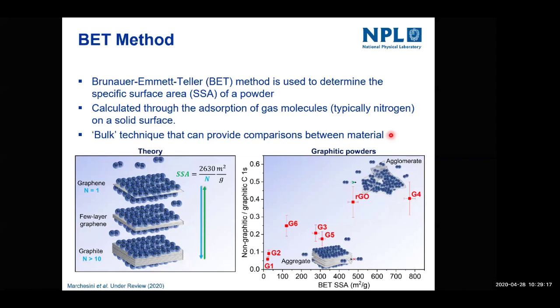But in a lot of cases, people will use that to try and calculate the number of layers, and that doesn't work. Theoretically, you could look at these values. So again, if you had this very high value of 2,630, you could argue that could correspond to individual graphene in theory. However, in practice, there are other variables that affect it. You generally get restacking of these graphene particles, graphene flakes. So you can get particles that might be very thin in the primary particles themselves, don't have many layers, but actually the specific surface area can be quite low because of this restacking.